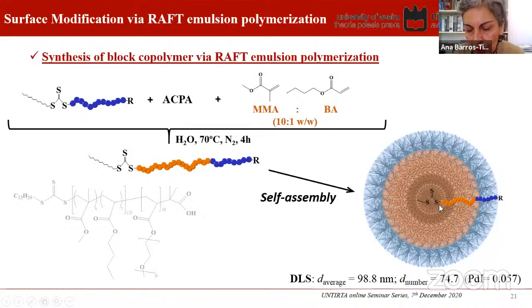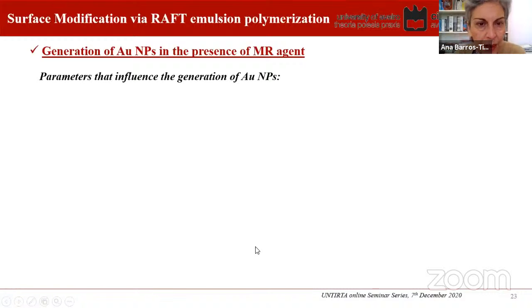One very short polydispersity. These particles were the ones that were then used to prepare the hybrids, either using a post-modification strategy or by preparing the gold nanoparticles in situ. As you can see in the images, the results weren't exactly as good as one would want, especially because we would have these patches of polymer without any particles, or we would have aggregation of the particles. So it proved that we needed to do more work.